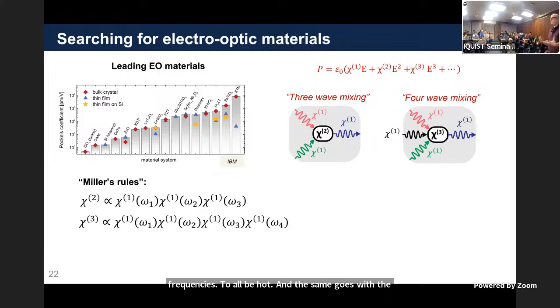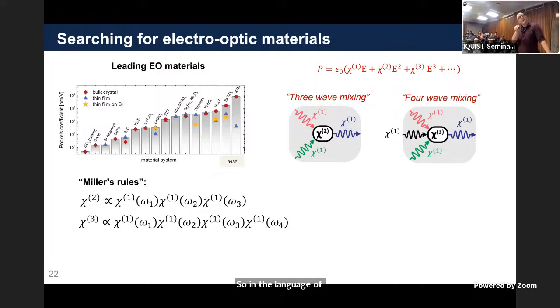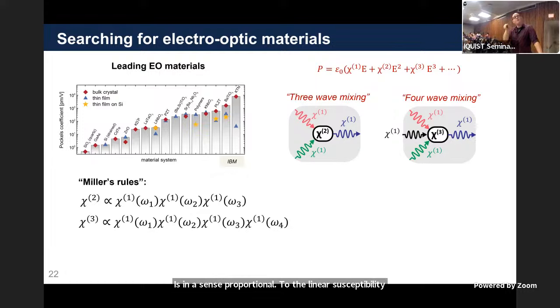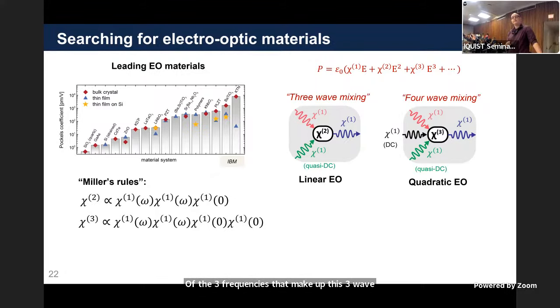So in the language of nonlinear optics, what that means is that the chi-2, this three-wave mixing process, is in a sense proportional to the linear susceptibility, or the dielectric constant or the index of refraction, of the three frequencies that make up this three-wave interaction. But just this simple heuristic actually can let us completely understand all of this trend here. And once again, this is the linear electro-optic effect where one of these frequencies is basically zero and one of them is an optical frequency.